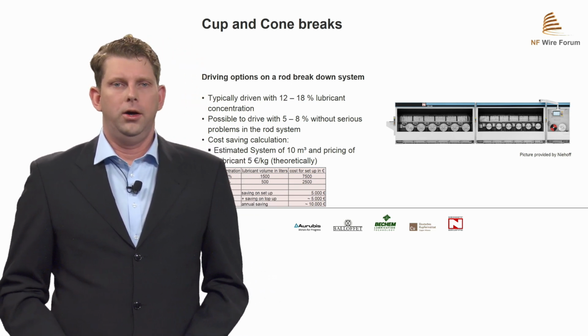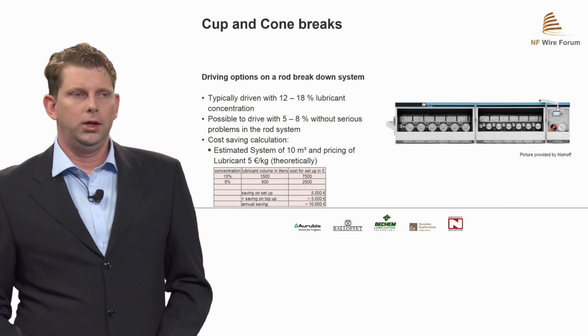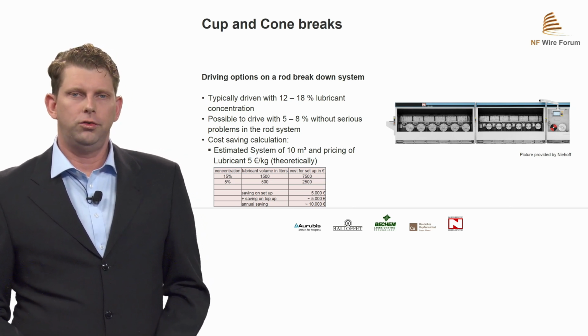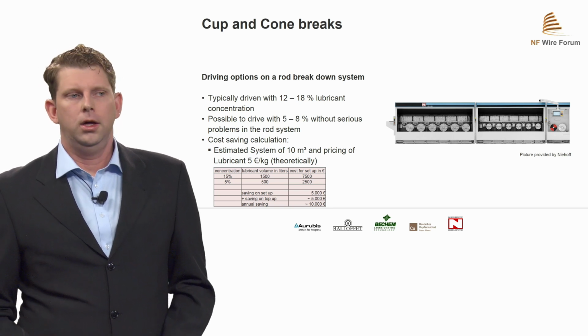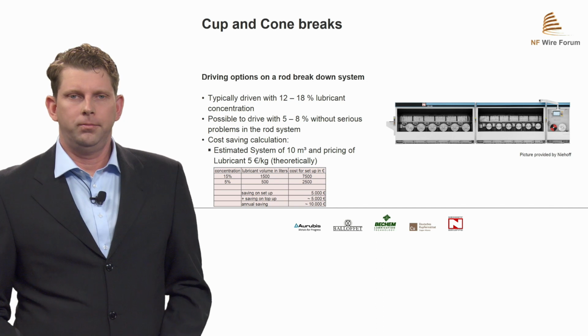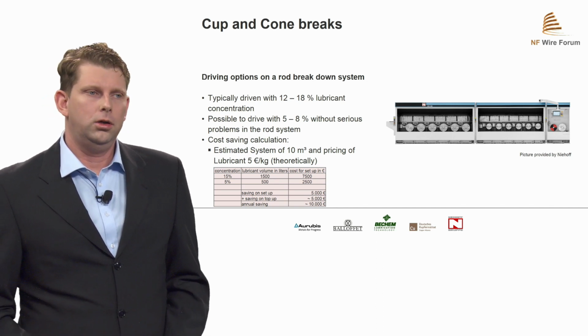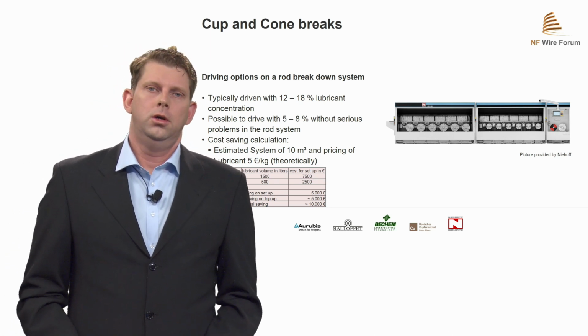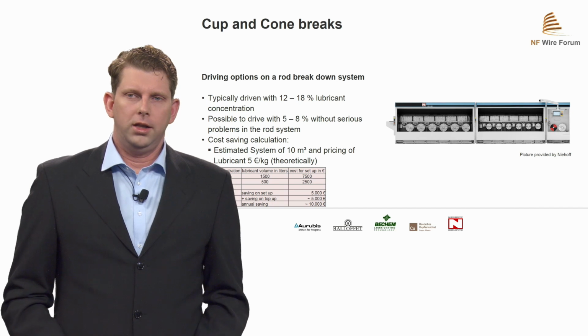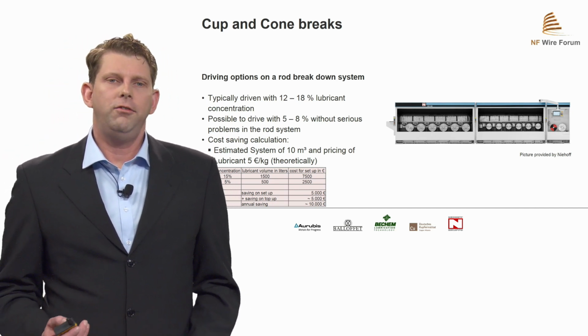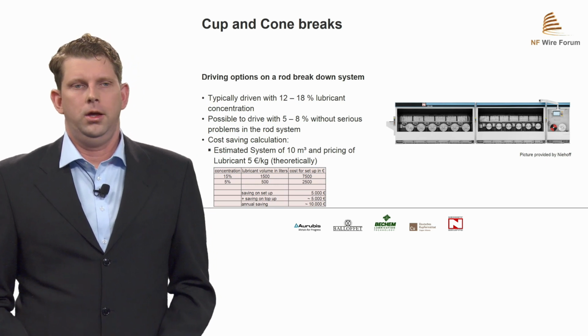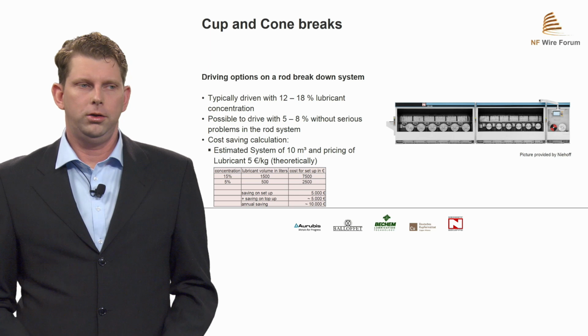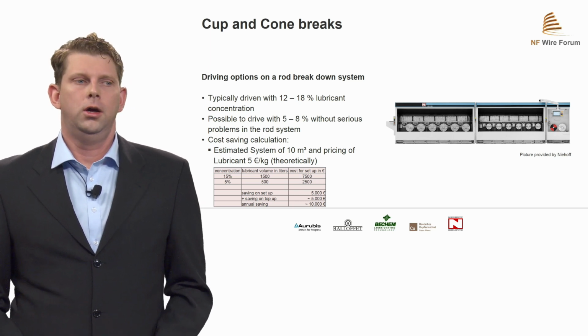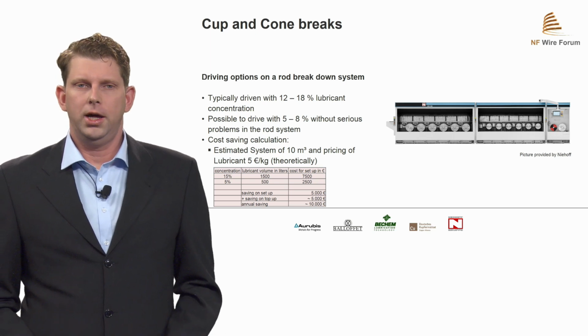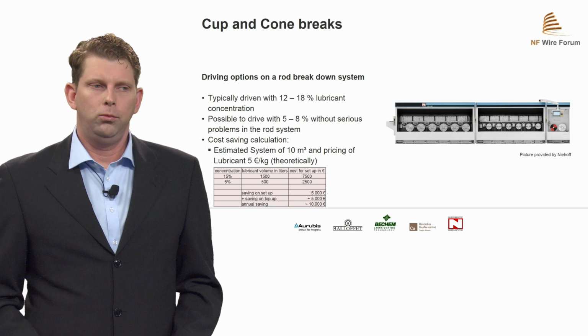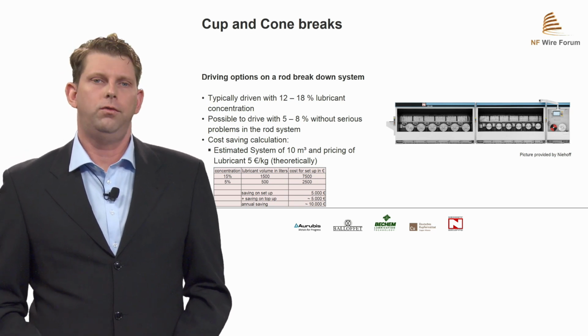So if we look at the rod breakdown, you can drive it with different drawing options. Typically, it is driven with a concentration of 12 to 18%, but it is also possible to drive it with 5 to 8%. But what is the result of this different drawing option? First of all, let us take a quick look on a saving calculation for the lower drawing concentration. Let us estimate a system with 10 cubic meters and a price of €5 per kilogram for the lubricant. So if we drive it with 15%, we would need 1,500 kilograms of lubricant and would rise to a price of €7,500 for the filling.